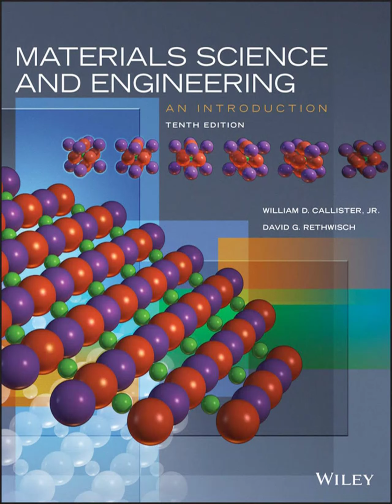Precisely. We're talking increases from maybe 1 to 5 units of toughness for standard ceramic, up to 6 to 20 units for a CMC. That's a huge improvement. How do they achieve that? Yeah, how do you toughen a brittle material? Several clever ways. One is called transformation toughening. It uses tiny particles of a material like partially stabilized zirconia mixed into the main ceramic matrix, say alumina.